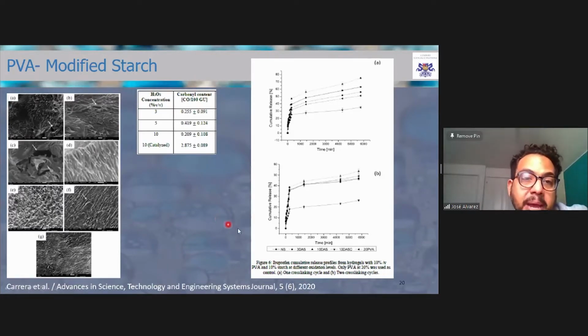Now, what we did in this paper was look at the effect of different oxidation degrees. And we found that we encapsulated here ibuprofen as a model molecule, model drug. And then we looked at the release of the ibuprofen from these hydrogels. And we found that there is a very important effect of the oxidation degree on the way the molecule is delivered. But also we found very interesting effects on swelling. So swelling is how much water they absorb, and the higher the oxidation degree, they were more stable, but the